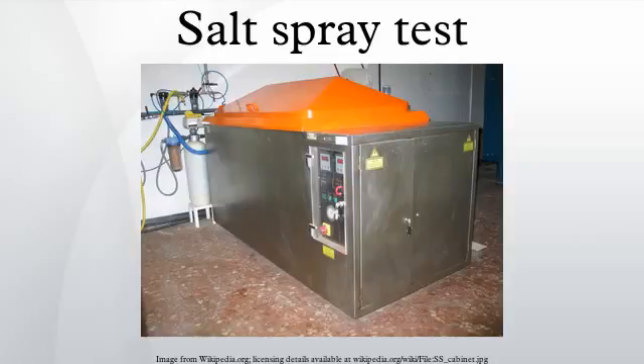Test specimens are placed in an enclosed chamber, and exposed to a changing climate that comprises the following 2-part repeating cycle: 30 minutes exposure to a continuous indirect spray of synthetic seawater solution, prepared in accordance with the requirements of the test standard and acidified by the addition of acetic acid. This spray is set to fall out onto the specimens at a rate of 1.0 to 2.0 ml per 80 square centimetres per hour.